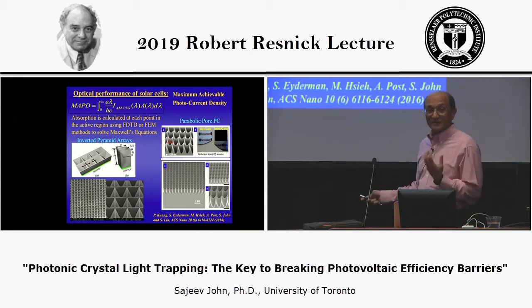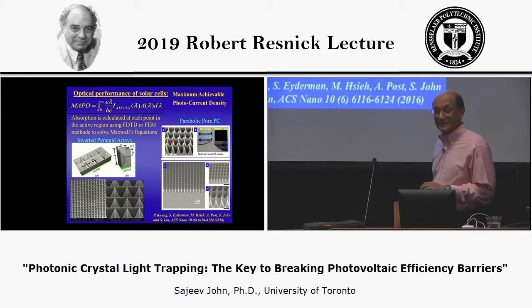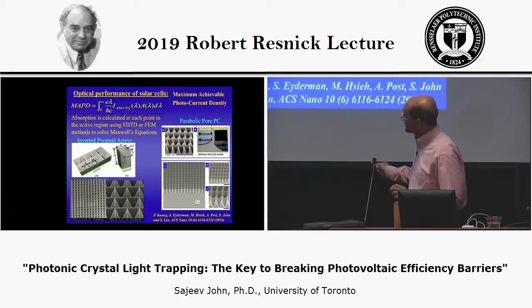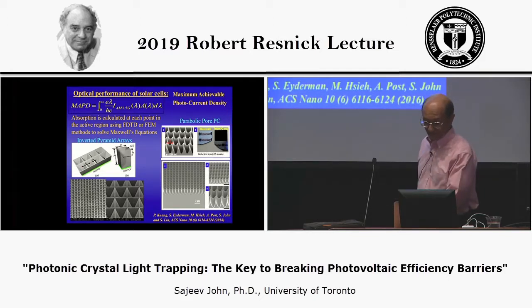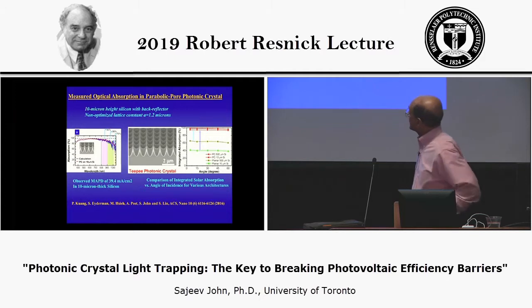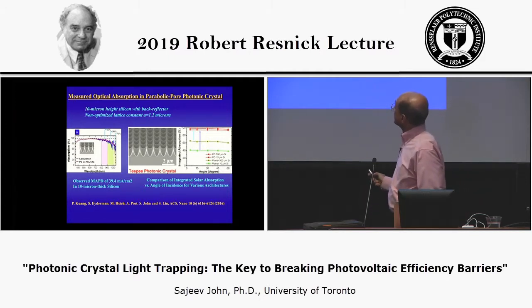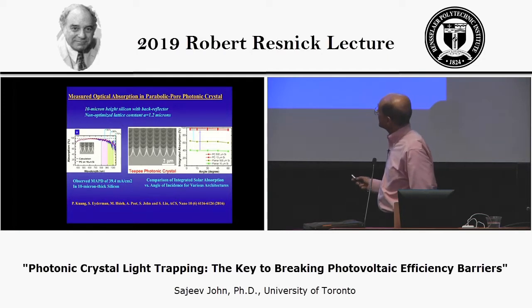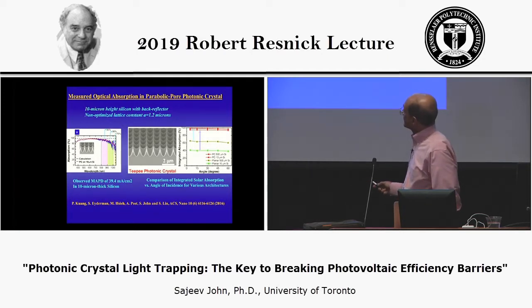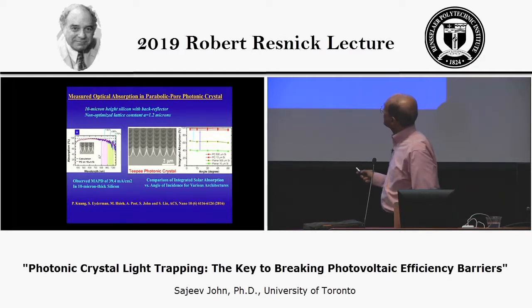And this also has a very strong light trapping capability, provided that the lattice constant is chosen appropriately. So here are some actual optical measurements in comparison with theory of the first structure, the parabolic pore structure, as a function of wavelength from 300 to about 1100 nanometers.